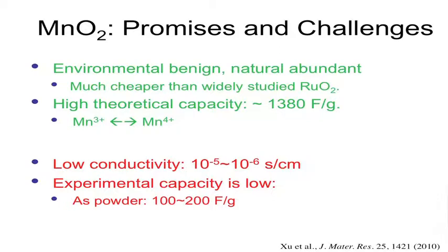Theoretically, MnO2 has a very, very high capacity, 1380 Farads per gram, but realistically, people can only achieve about 100 to 200 Farads per gram in real devices simply because MnO2 is a very, very bad conductor. So you can only use the surface of the material, not the whole structure, for the energy storage. So my approach is to use carbon material to solve this problem. I'm not the only one to do that.